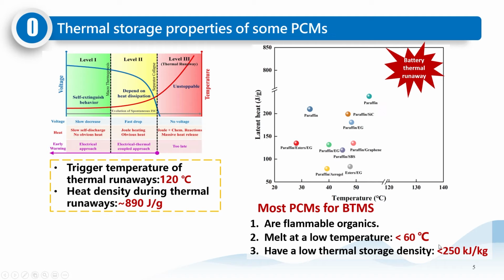In most PCMs we used for battery thermal management systems, we found that most of them are paraffin. We can see from these figures in the right figure, most are paraffin, and they are flammable. So when the PCM itself gets on fire, it could make the case worse when the battery is encountering thermal runaways. And in another aspect, most PCMs melt at a low temperature, and most of them have a melting point below 60 degrees C, which is unmatched with the thermal runaway temperature of the battery.